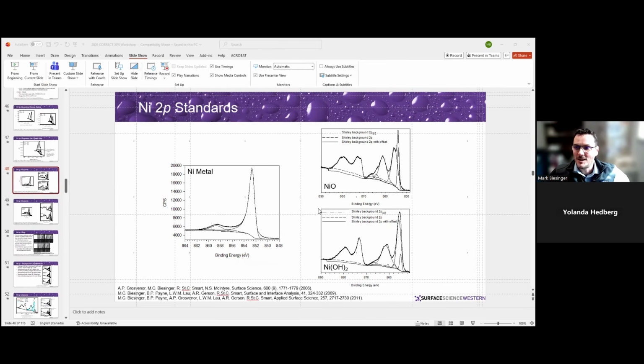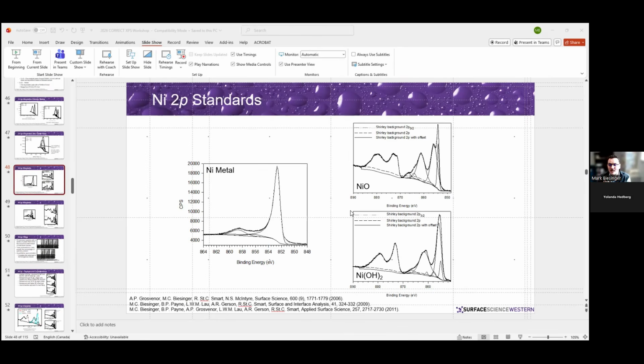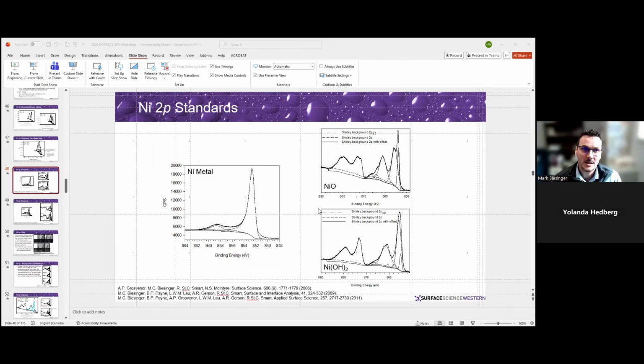You'd have to look at your experiment and try to justify as to why there isn't a carbide. But there's not much else down at that carbon 1s peak. And if you can rule out differential charging, so you're doing your analysis and you change flood gun settings and things like that, and the peaks don't move around, everything stays stable, then if it's a carbide, it's a carbide. But you'd have to rule out those other things.